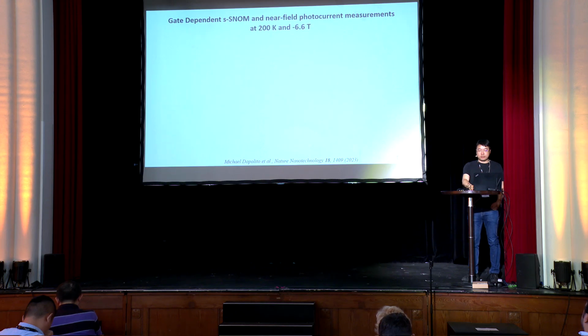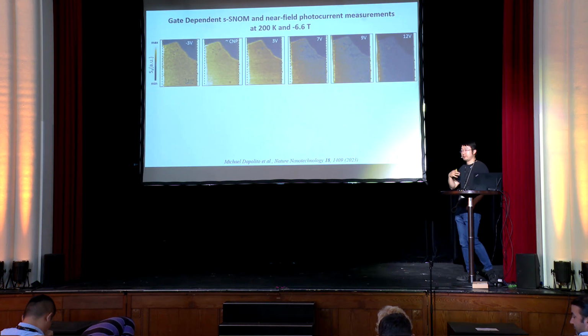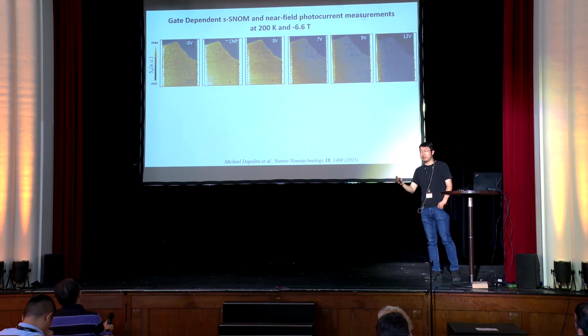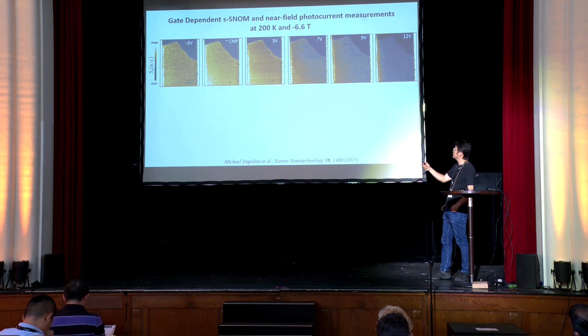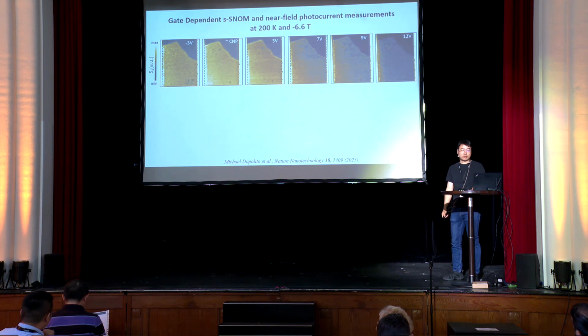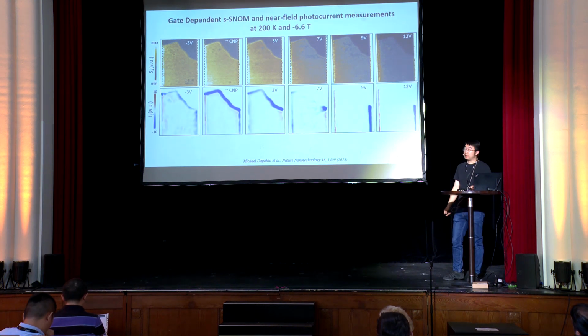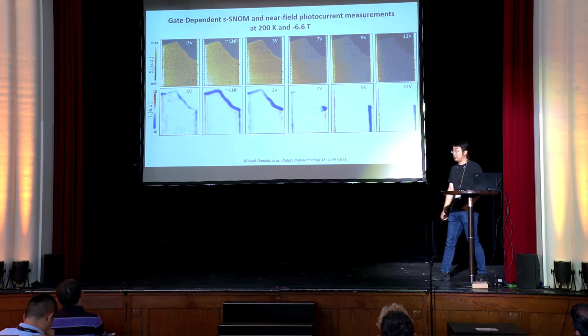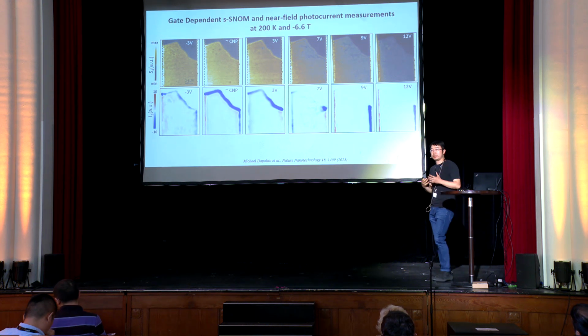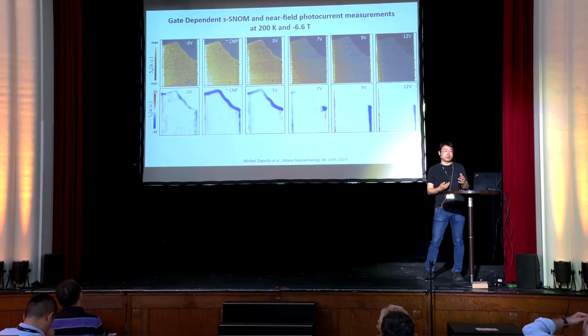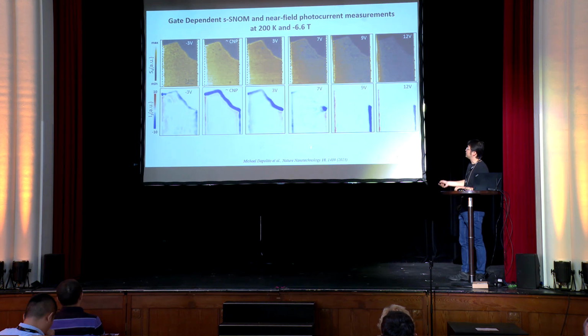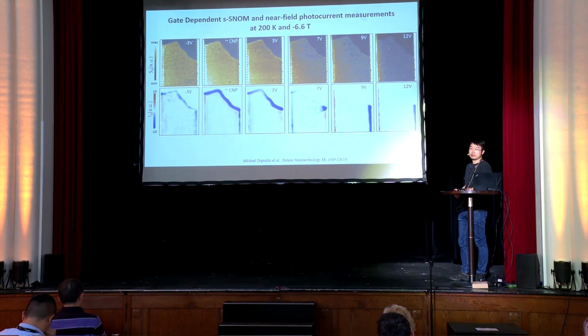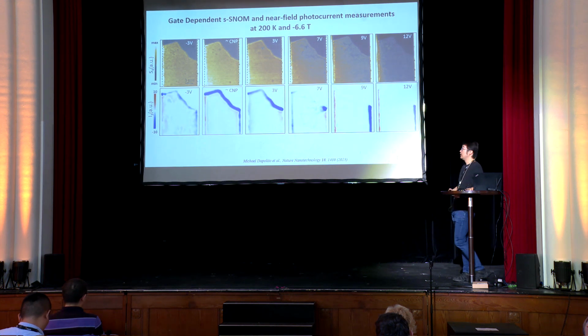You can also do this in photocurrent in gate-dependent measurements. So you basically block the 0 to 1 transition by applying a gate, right? You can block away the transition and make this bright contrast go away. In the photocurrent, you can also gate it away so that you do not have these edge channels anymore. So this is nice, right? We can now access Landau level physics in real space and see these edge channels that can potentially be topological in many different material systems.